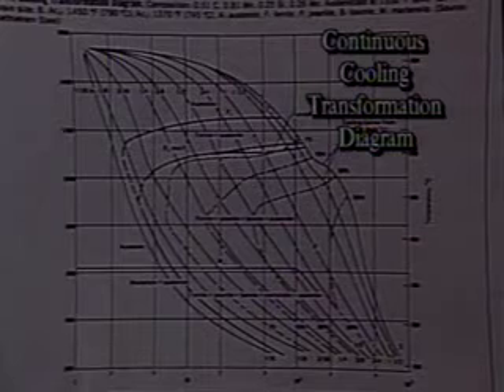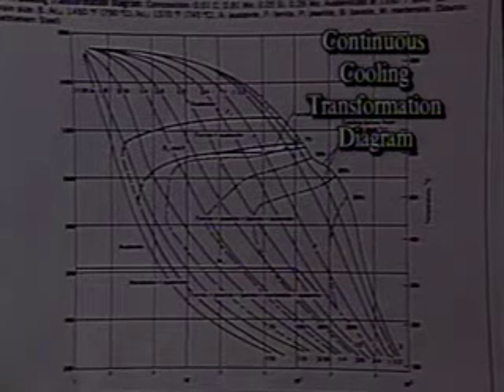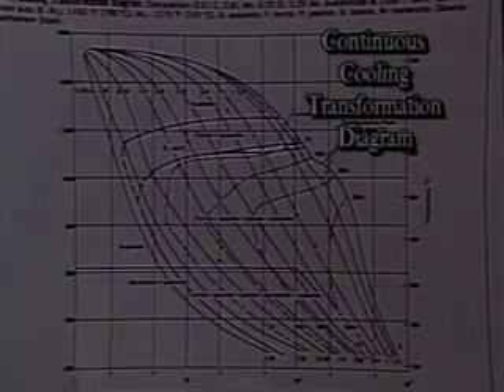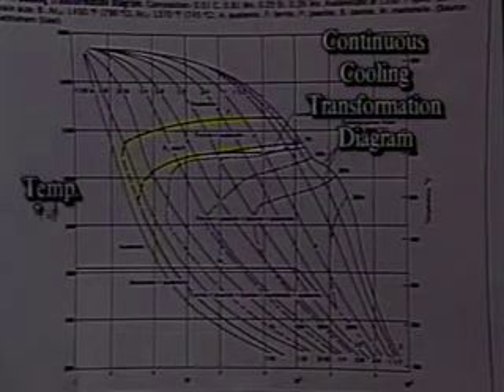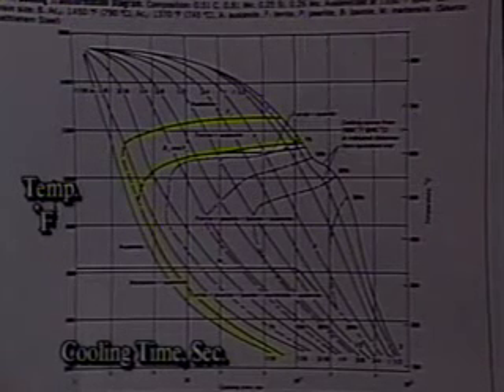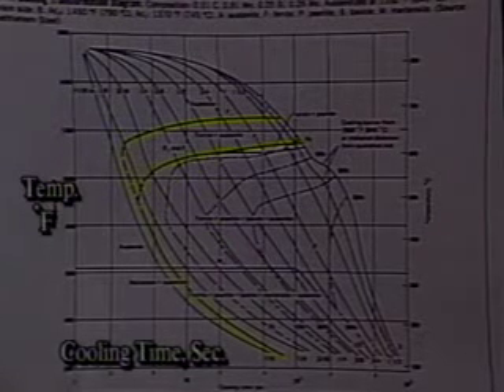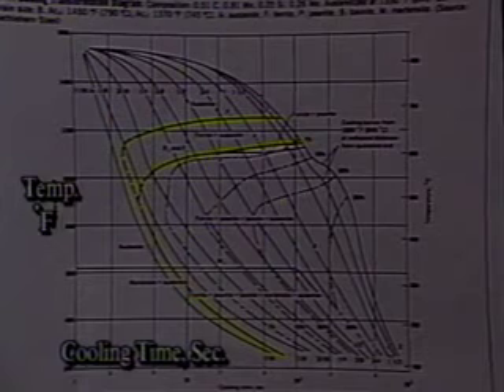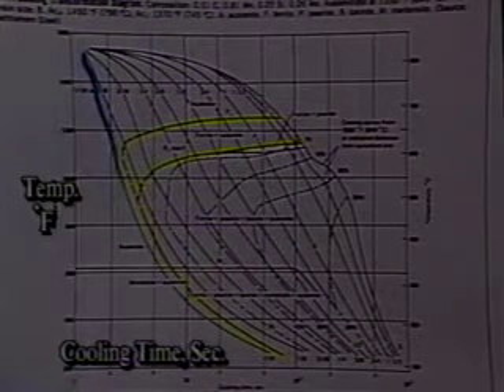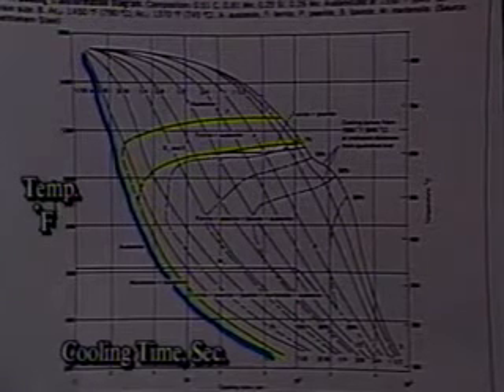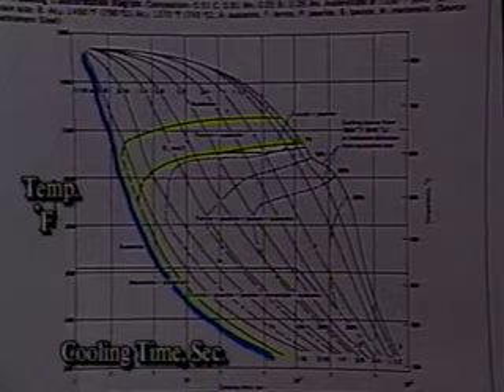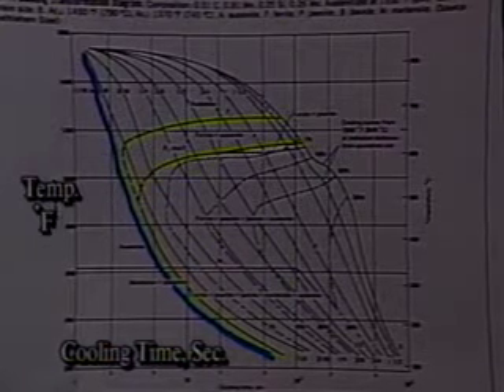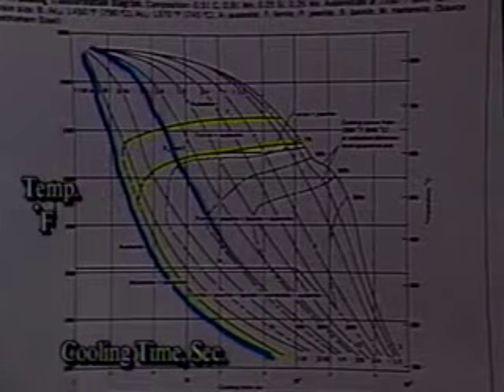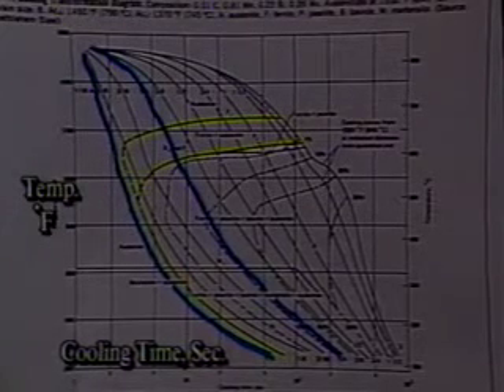The isothermal diagrams and continuous cooling transformation diagrams help us predict the phases that will form during quenching. This is a continuous cooling diagram, or CCT diagram as it is usually called. These curves indicate the time and temperature at which the alloy begins its transformation from austenite and completes its transformation. For instance, a 1/16 diameter rod of this material will cool fast enough to miss the nose of the curve and transform completely to martensite. By comparison, a 1/4-inch diameter rod will take longer to cool and thus produce different phases in the material.